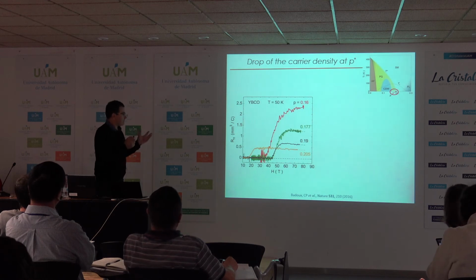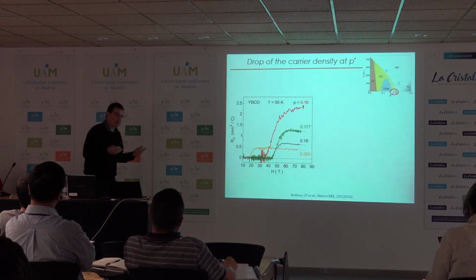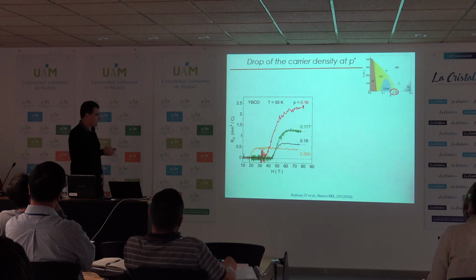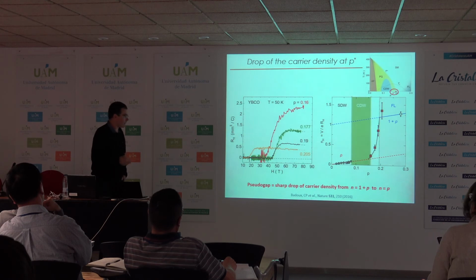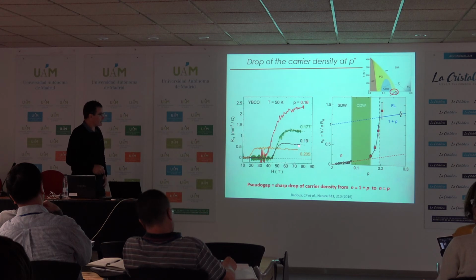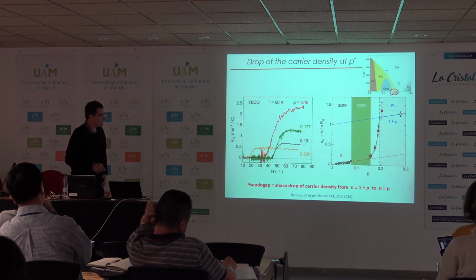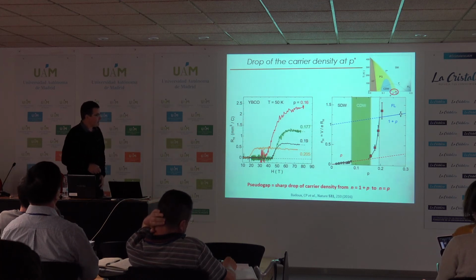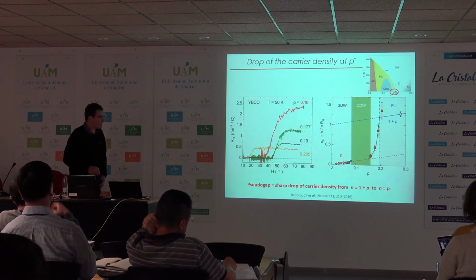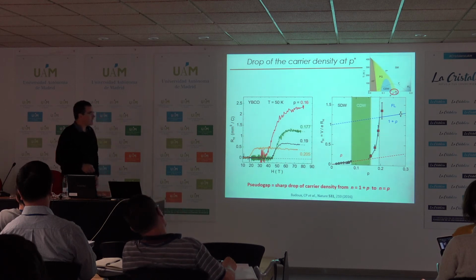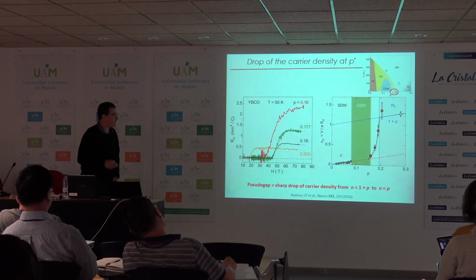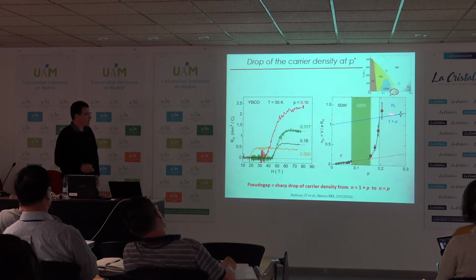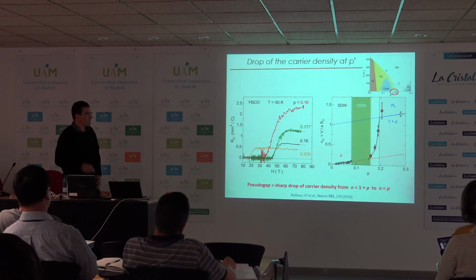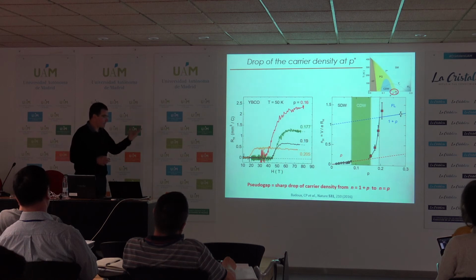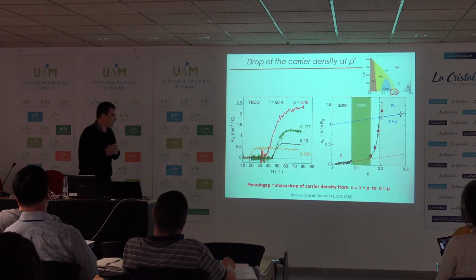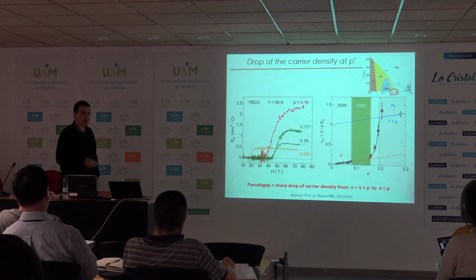And if you now naively translate the Hall coefficient in terms of carrier density, like done in basic condensed matter books, and you plot the Hall carrier density versus doping, this curve here translates directly to these four points here. What you can see from this graph is that at low doping, as we know from previous measurements, the carrier density is given by p, the doping. Whereas at very high doping, as I showed you before, in strongly overdoped thallium 2201, the carrier density is 1 plus p. And the transition from 1 plus p to p seems to appear at the critical point of the pseudo-gap, meaning that the pseudo-gap corresponds to a sharp drop. This is a factor of 6. It's really a sharp and strong drop of the carrier density between the two limits, 1 plus p and p.